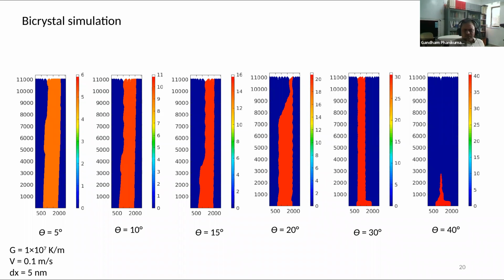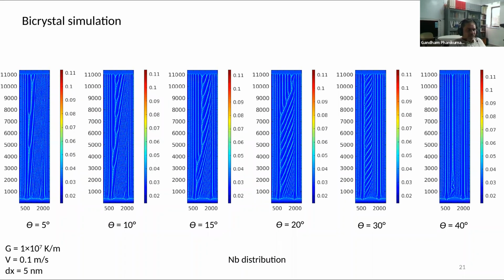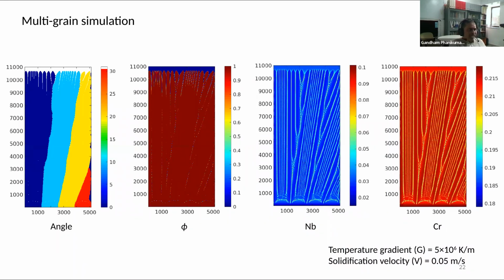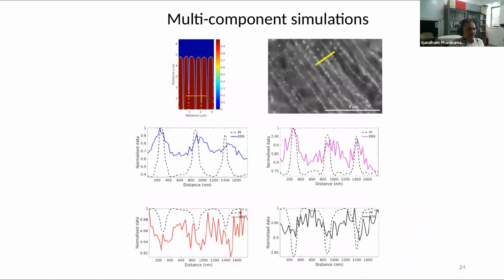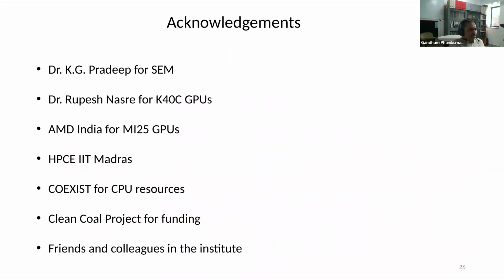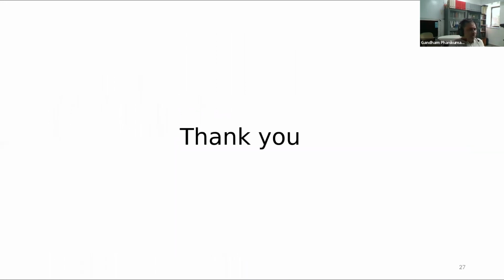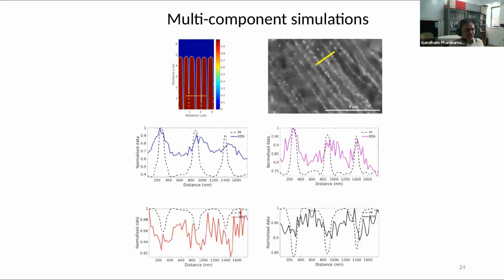Is crack formation a big deal? Of course. Those who are practicing additive manufacturing know that when they go to certain alloys, they simply cannot make the cracks disappear, and that is where we need to understand that quite well. We can also do this for not only 2 grains, but for multiple grains to understand how the segregation happens and how the grain boundaries are actually locations of slightly higher segregation and so on. Okay, and of course, these are also benchmarked with respect to experiments. So we have to, of course, thank our colleagues for their help in doing these simulations. So I stop here and see if you have any questions on this aspect of microstructure formation before I move on to the remaining aspects.